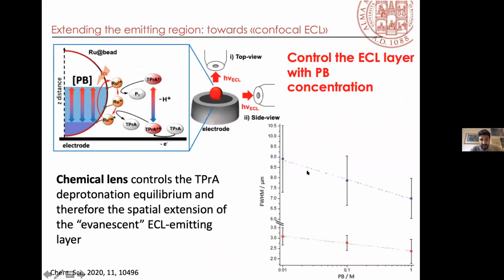That is quite interesting. For the next step in this field of application, I am fully convinced that we need to find a way to control the emitting layer. So this 1 or 2 micrometers, we need to find a way to control this active zone. In this example, we just published a paper where we demonstrate that with a chemical lens we can control the emitting layer. By controlling the phosphate buffer concentration, we can decrease or increase the ECL active layer of 1 or 2 micrometers, depending on the phosphate buffer concentration.